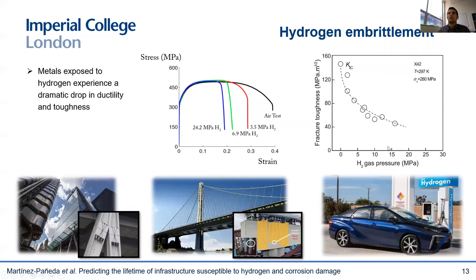So hydrogen makes our otherwise ductile metals very brittle. And this, of course, has tremendous implications, as hydrogen is the third most abundant element on the Earth's surface. Thus, hydrogen embrittlement has been a well-known concern in offshore engineering, where metals are exposed to particularly aggressive environments. And the problem has gotten significantly worse through the years for mainly two reasons: the higher susceptibility of modern high-strength alloys used in buildings, bridges, and railways, and of course, due to the promise that hydrogen holds as energy carrier of the future. We already have hydrogen-fueled cars, buses, and trains in the market.